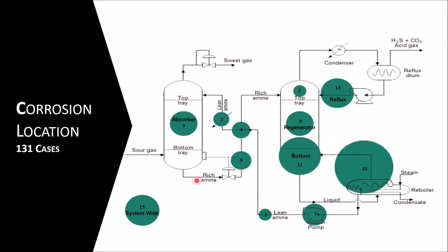It makes sense because the temperature is moderated here. It isn't until we start to heat up the rich amine that we can have rich amine issues. So temperature is a key. Look where all the corrosion occurs: reboiler, regenerator column bottom, mid, reflux, lean pumps, lean amine piping, coolers. What's common about all these locations is temperature. They have the least amount of acid gas down here, but they have the highest temperature. And temperature is always going to aggressively increase rates of corrosion.